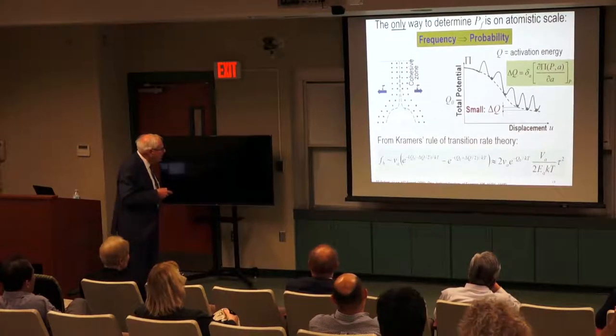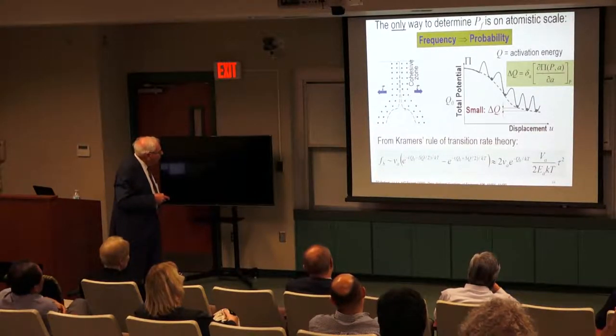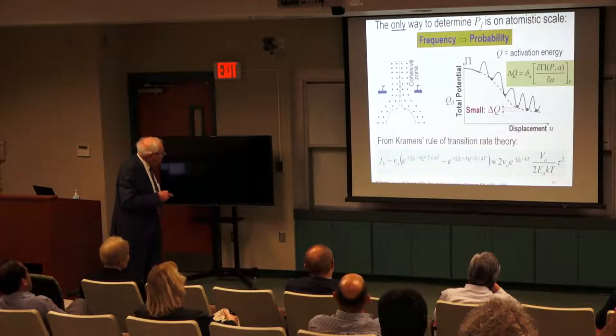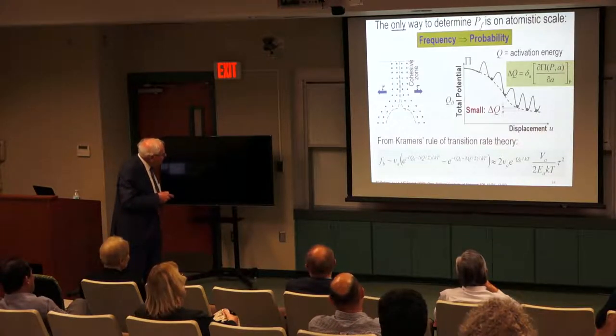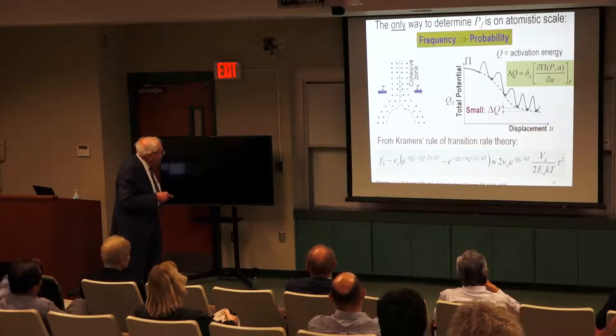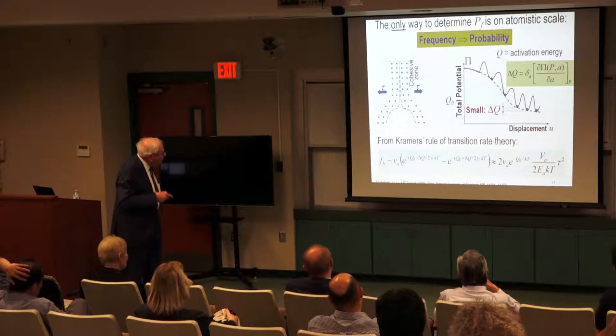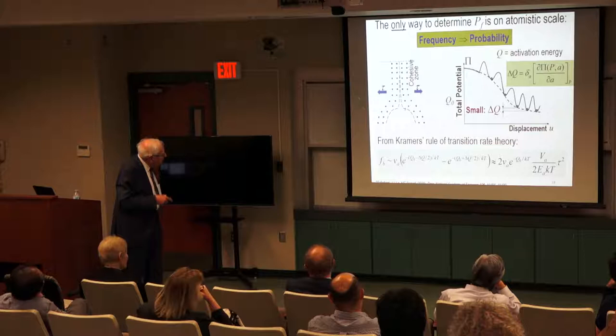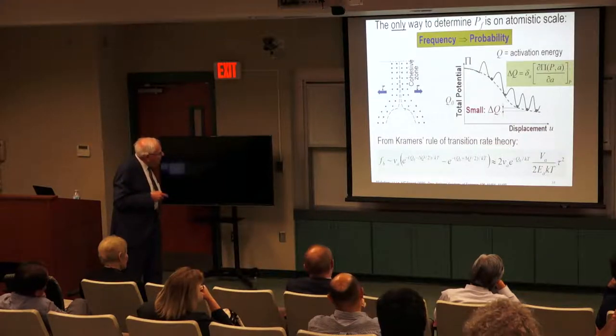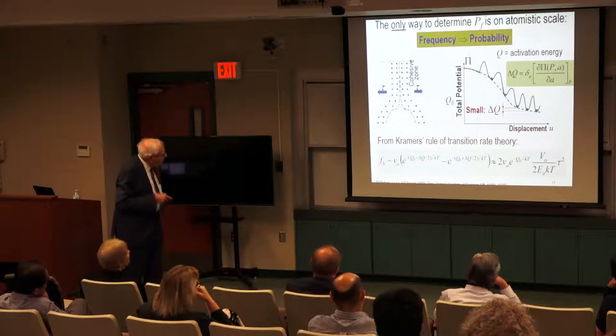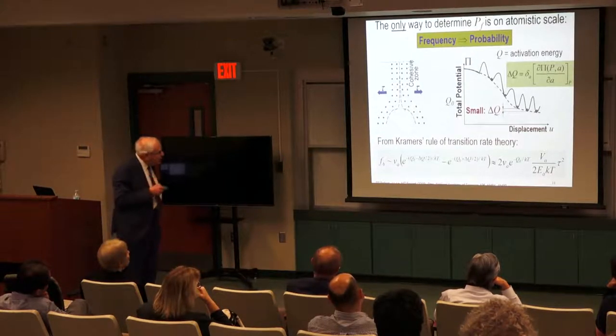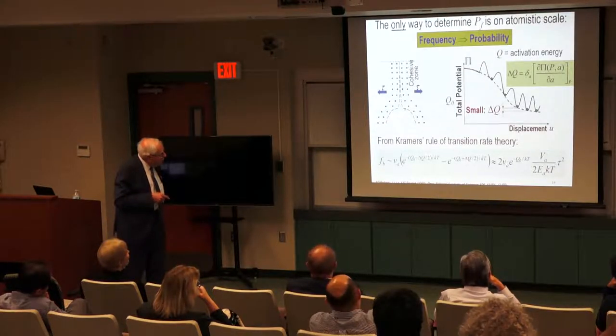It's similar in disordered materials. Before you advance the open crack, it has to advance through the lattice by steps, obviously. So it's either here or there. And this discrete motion superimposes an undulating potential on the smooth potential which you normally derive for this nanoscale zone. So the total potential decreases as the displacement of the crack grows, with this superposed. The main point here is that these waves are numerous, in fact thousands, so the difference between the valleys is very small.